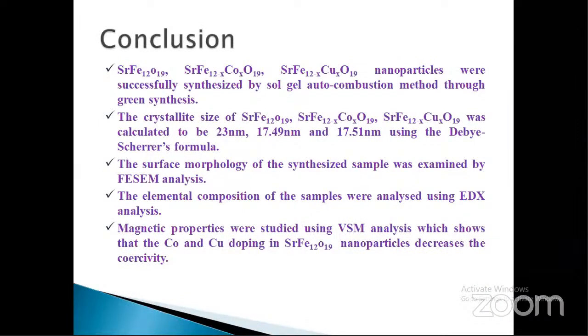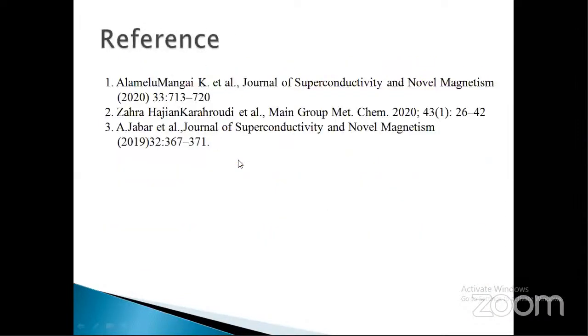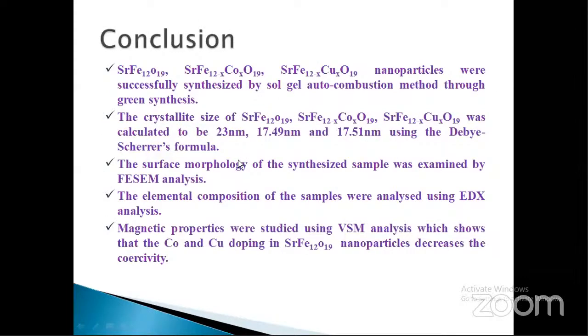So strontium hexaferrite and cobalt and copper-doped strontium hexaferrite nanoparticles were successfully synthesized by the sol-gel autocombustion method through green synthesis. The crystallite size of undoped and cobalt and copper-doped strontium hexaferrite was calculated to be 23 nanometer, 17.49 and 17.51 nanometer using the Debye-Scherrer formula.